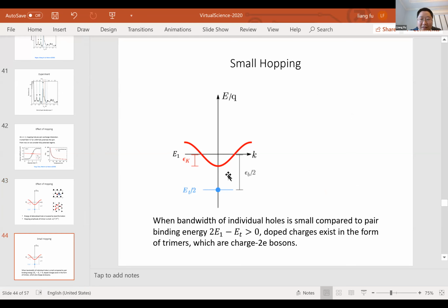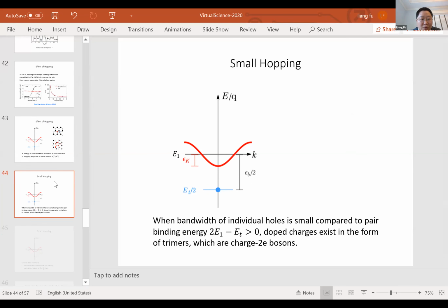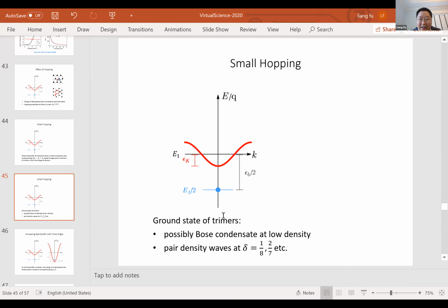Okay, so when the hopping is small, the bandwidth of individual holes is small compared to the binding energy. Then when you dope the system, the doped charge directly goes into the trimers, which are charge 2e bosons. So we don't need to consider the effect of holes to leading order. And in this case, as I said before, the ground state can be a pair density wave at these commensurate fillings, or away from these fillings, the ground state can be a superfluid, a Bose condensate of these charge 2e trimers. This will be a very strong coupling picture.